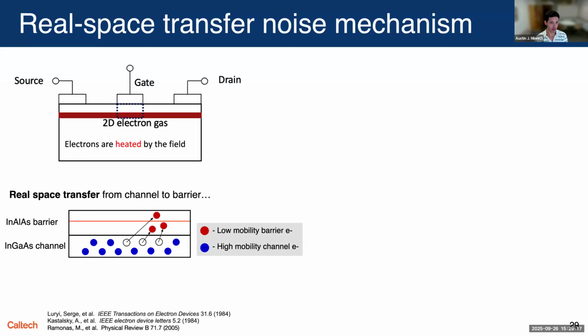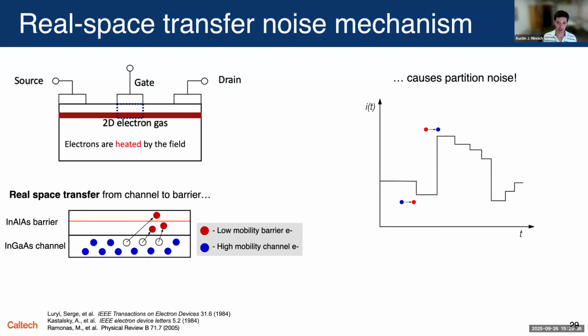When that happens, the electrons actually are hot enough to thermionically emit out of the channel and into the barrier. Those two films have very different electrical transport properties, with the channel being highly conducting and the barrier not. And when you have that situation, it's kind of the classic case of what's known as partition noise. And that occurs when there's two paths to the same final contact, but they have different transport properties.